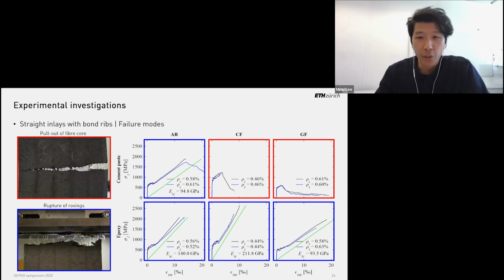And this normally occurs due to insufficient penetration of the coating into the roving, and we can see that this type of failure did not happen with epoxy coating, and all these specimens here exhibited hardening, good utilization of strength.